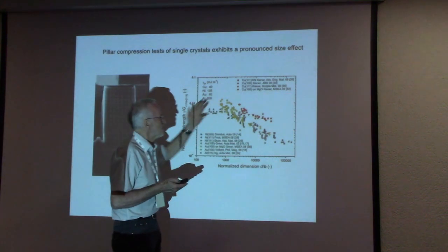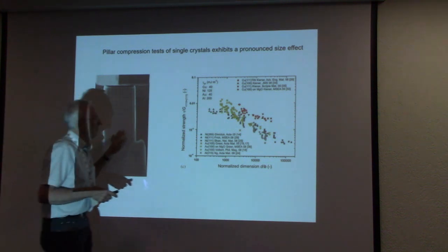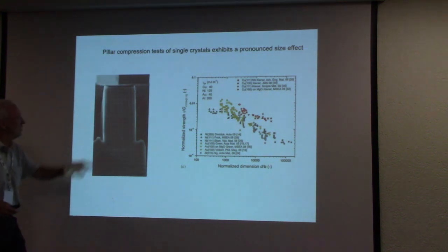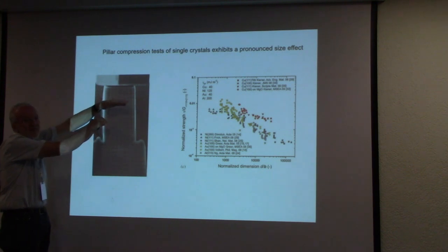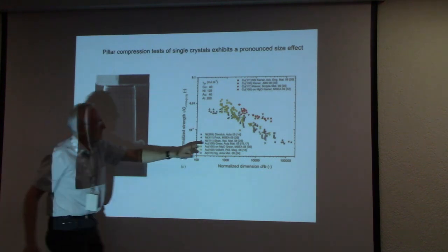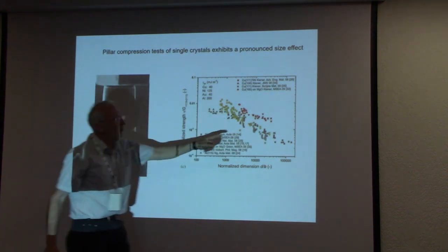increase in yield stress. There was really a big discussion about 10 years ago: we have a compression experiment where we assume a homogeneous stress distribution in this area, yes, and we get a yield stress variation of, again, more than 1 order of magnitude. Yes. So, what should we do?